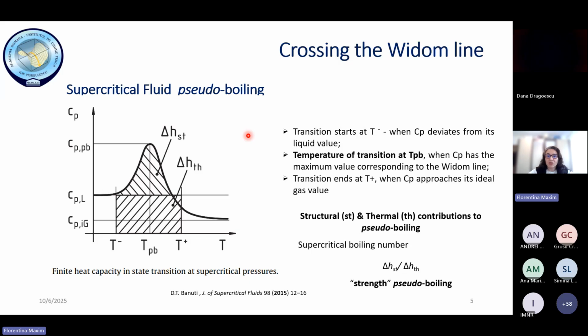But the difference between boiling and pseudo-boiling is that the energy given to the system is consumed both for the structural changes, but also to increase the temperature of the fluid. Because of that, there are two contributions to the pseudo-boiling, a structural one and a thermal one. And the strength of this phase transition is practically determined by the supercritical boiling number, which is the ratio between these two contributions.